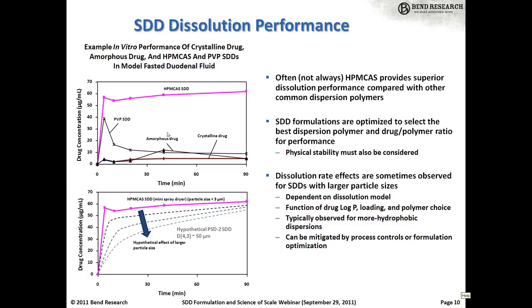So in terms of in vitro dissolution performance, this is a model drug example. It's an HPMCAS SDD, a PVP-based SDD, amorphous drug alone, prepared by spray drying without a polymer, and then a crystalline drug. And this is a typical microcentrifuge type of dissolution study in a simulated intestinal fluid. What you see is what's often seen, in that the SDDs both provide rapid dissolution and supersaturation, although the PVP SDD in this case crashed out quite rapidly, whereas the HPMCAS SDD continued to provide that good sustainment that you really want to see. And that is often, but not always, the case.